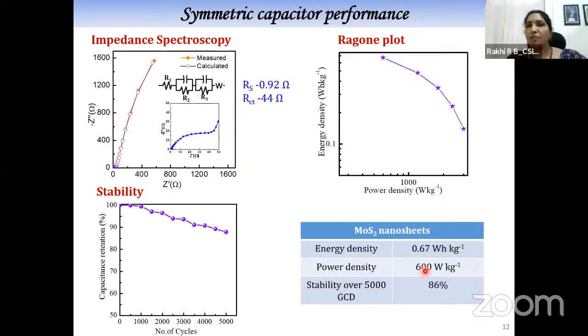We can compare it with the performance of graphene. When we make graphene by RGO, maybe just before this there was a talk by Dr. Biju, so I am not sure how much value he has reported, but usually if you have a perfect RGO sample, when we do the supercapacitor measurement at a current density of 1 ampere per gram, we should get something around 150 to 200 farad per gram of specific capacitance for 1 to 2 milligrams of active material. But for the same active material, we are getting only 13 farad per gram for the MoS2 sample. So this is not useful. Why should I work on this material?